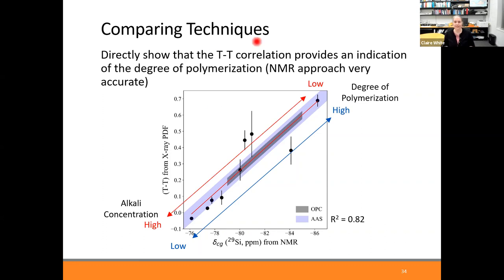And so what we find is when you have a high degree of polymerization, we have low alkali concentration, low amount of sodium. Whereas if we've got a high amount of sodium, we have a low degree of polymerization. What's shown here in gray is the span for the gels that tend to be in Portland cement concrete. And what's shown here in the purpley blue is the span that we have for the gels that exist in alkali activated concrete. So it's important with the chemical composition of your system to choose it carefully, because it's nice to be in this region. We're going to have a more polymerized gel. It's likely going to be more stable compared to if we're down this end on the plot.